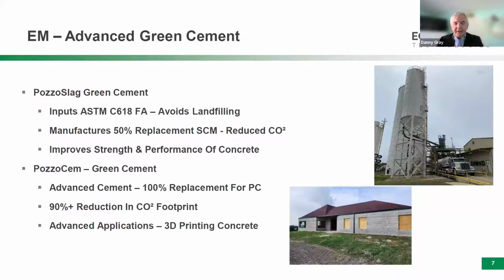In the field of advanced green cement, in our company's case, we manufacture a low carbon footprint green cement that uses coal fly ash as an input and avoids landfilling. We are able to manufacture a product that has a 50% replacement ratio. So instead of 600 pounds of cement in that cubic yard, we would replace 50%, or 300 pounds of cement, and that is a way to help reduce the embodied CO2 in the material.